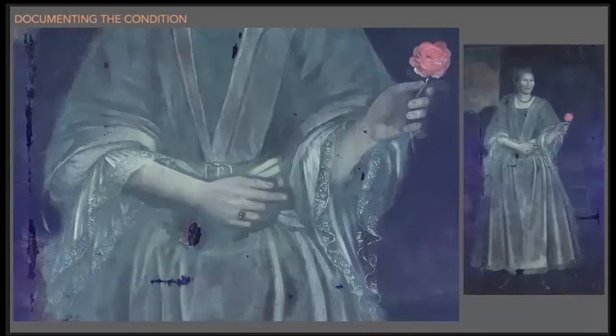In addition to noting the retouching and surface coatings in UV, we can also take note of certain pigments that fluoresce within the UV light spectrum. One such pigment is Red Lake, shown here as a pink fluorescence in the rose held by the sitter. While the fluorescence of the surface coatings over the painted surface tends to subdue the fluorescence of most pigments, certain ones, such as Red Lake, have such a strong fluorescence that their presence can be, at times, easily detectable.